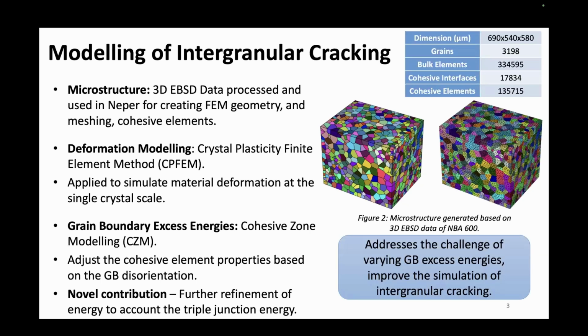Before moving into the simulation, we need to create realistic finite element structures. One way of obtaining such microstructure detail information is by using 3D EBSD. From the 3D EBSD data, we develop a procedure that integrates Neper for creating finite element method compatible geometry, including grain tessellation, meshing, and inserting cohesive elements. And here is an example structure we created with that procedure, with the details about the finite element model. Those grains are colored by grain orientations.